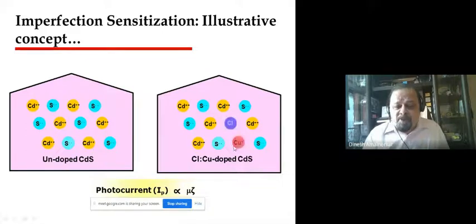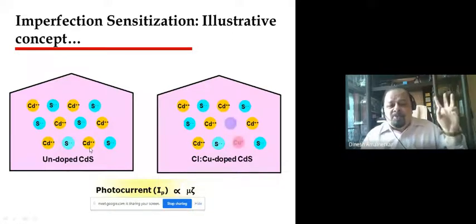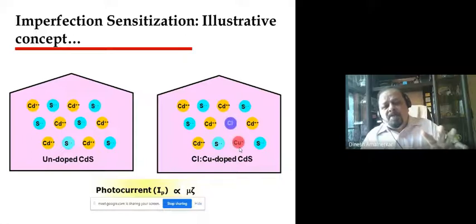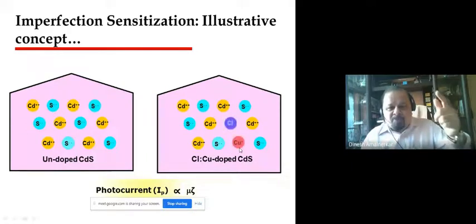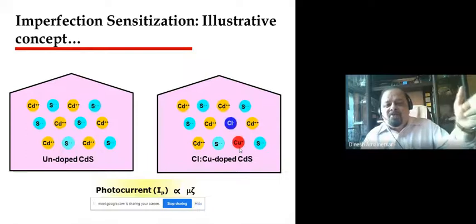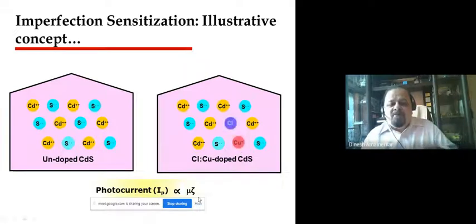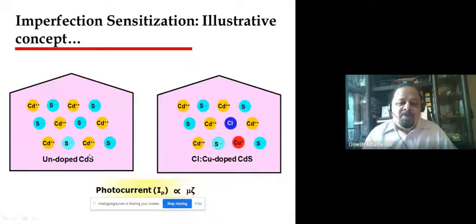Now, Cu+, because of its only one positive charge, is supposed to have effective negative charge in comparison to two positive charges of Cd+2. It has two positive charges. It has only one positive charge. So this is supposed to be considered as a site with effective negative charge. Since it has effective negative charge, probably it exerts Coulombic repulsion for the photoexcited electrons in the conduction band. And since the photoexcited electrons spend a lot of time in the conduction band, the tau, here the proper tau, increases. And since tau increases, photocurrent increases. That situation is not available here.